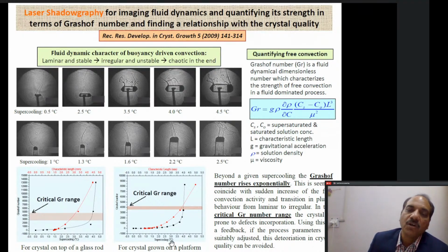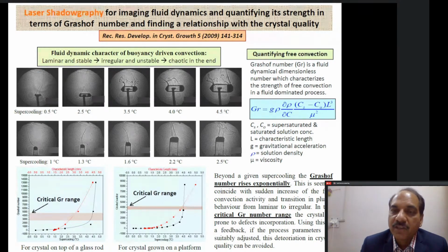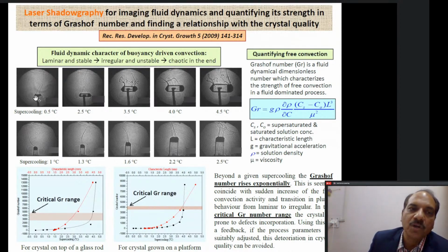So we thought, why should we not quantify this? Again we took the cue from fluid dynamic literature, which refers to the Grashof number. Grashof number is a fluid dimensionless number which characterizes the strength of free convection in a fluid dominated process. Crystal growth from solution is a fluid dominated process, and we calculated the Grashof number at all these 5 stages of 2 different experiments. In one experiment, the crystal has been put on top of a capillary tube, and the crystal is growing. In the other experiment, you will see that the crystal has been put on a platform and the crystal is growing in size.